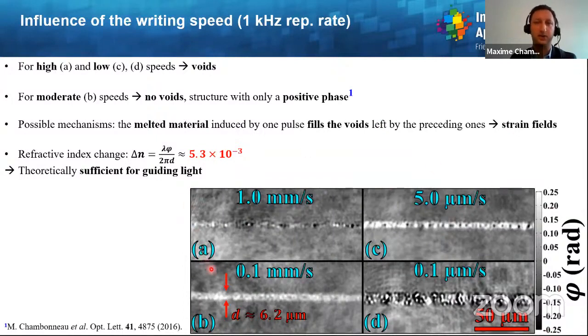inscribe some lines inside the material at different scanning speeds, so different feed speeds. What one can see is that for high and low speeds, you can see some black dots in the phase images, which are related to some negative phase shift, meaning that there are some negative index changes, which have to be related to voids or microcavities inside the material.